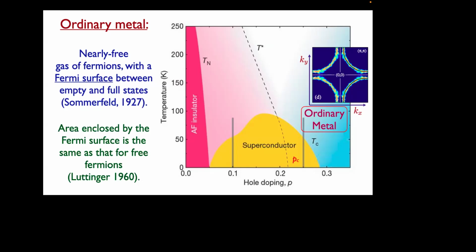A very deep theorem due to Luttinger, in fact, here at Columbia, was the following: that even after you put in interactions between the fermions, the shape of this Fermi surface would change, but its area could not. The area enclosed in this region should be independent of essentially everything other than the density of electrons. Once you know the density of electrons, you can deduce what must be the area enclosed by the Fermi surface. So this very deep theorem, again, is the foundation of solid-state physics. And if you apply it here, you find it works beautifully. Even though these are very strongly interacting electrons, you measure the area enclosed by the Fermi surface, and you find it's exactly the free electron value. So that's great. That seems to work.